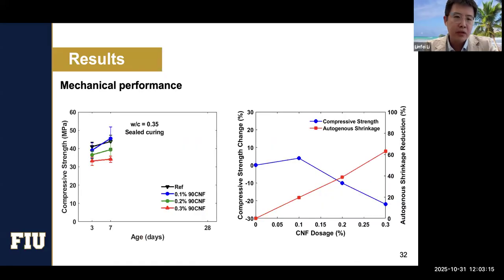We also did some mechanical tests because remember, we're trying to use the nanomaterials not only as an internal curing agent, but we also want to see if they can improve the mechanical performance. So now we're only able to show some results from 7 days, but it's kind of tricky because when we add 0.1% of CNF, we see a slight increase in the compressive strength. But if we add more, 0.2 or 0.3%, we see over a 10% drop in the compressive strength.